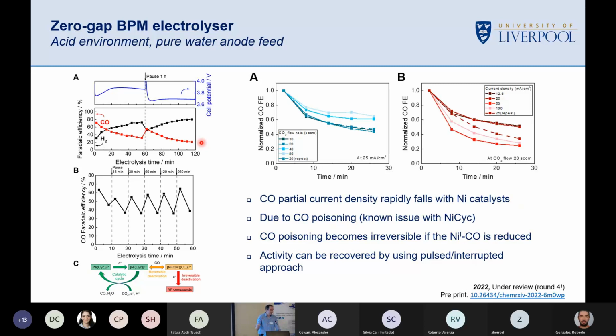You can then take it back by making the potential more positive again. The CO will be released, you're happy. If you go further negative, you can reduce the nickel 1 carbon monoxide and irreversibly destroy the catalyst. So at high current densities, this device fails much above 100 milliamps per square centimetre, pushing it too hard.